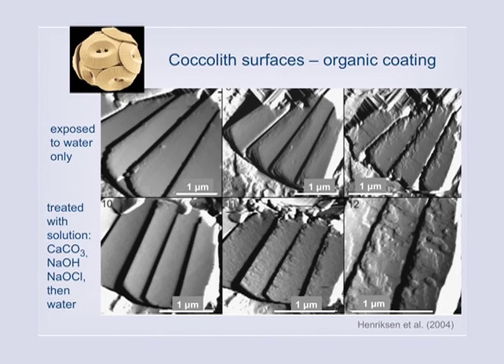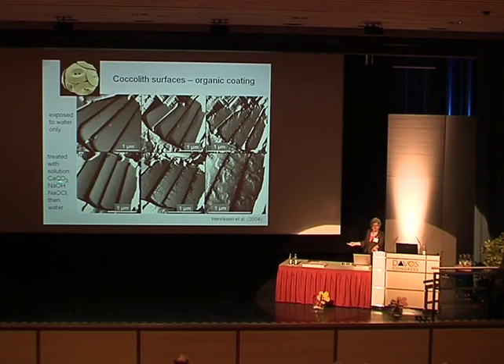If we expose these fresh coccolith elements to a solution that's at saturation with calcium carbonate, so we're not dissolving from this treatment solution, and it has a strong base and a strong oxidizing agent, and we leave it for some hours, and then we rinse it off with water and leave it exposed to water for a while. Now, we don't just get dissolution along the edges, but right out there on the flat. And here you can see a very eroded calcite crystal. Now, what's that telling us? It's telling us that something that is oxidizable is coating the surface.